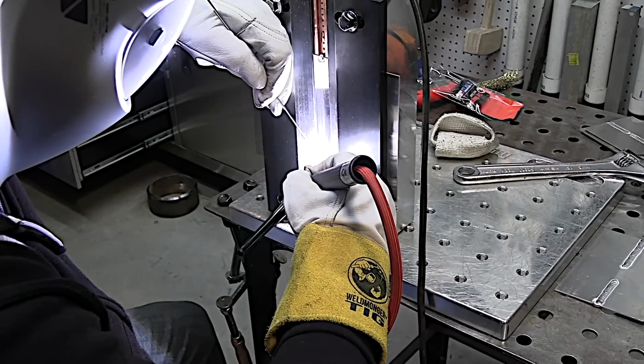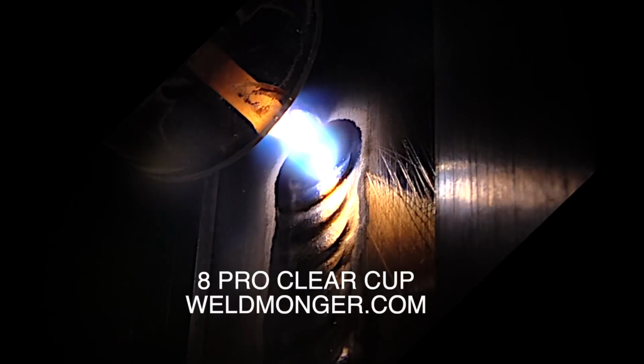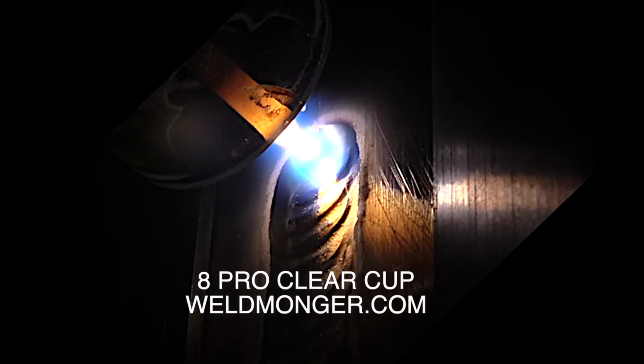Certain industries like aerospace use thinner metals, and the testing sometimes requires X-raying. Now on an X-ray weld, too fast a travel speed can trap gas and cause porosity. Oftentimes, test welds done for the aerospace industry are done in a fixture like this, which is a chill block, which speeds the cooling rate.